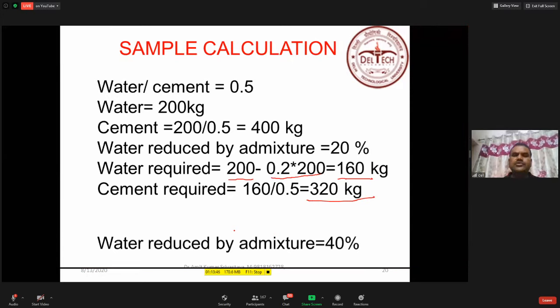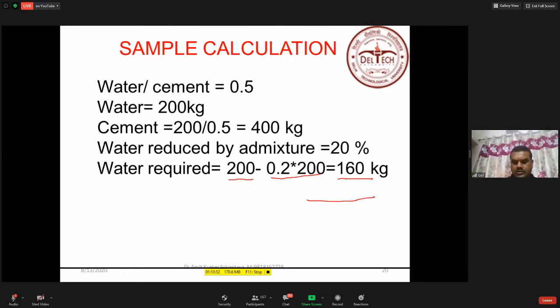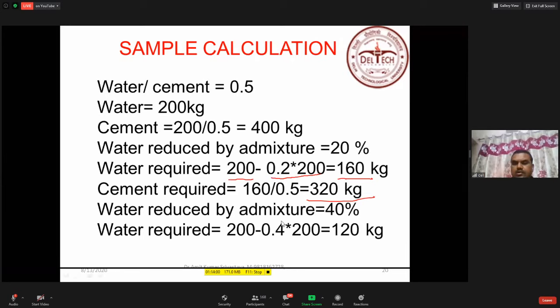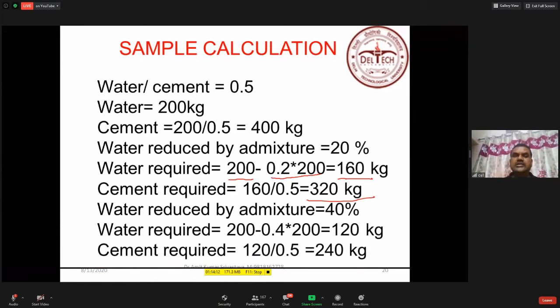Now suppose I'm using another admixture which can reduce the water by 40%. So if 40% water is reduced, then what happened? You see, water required is 200 minus 0.4 into 200. So 0.4 into 200 is 80. So now water required will be 120 kg. And you know, the water cement ratio is 0.5. So 120 divided by 0.5 will give you 240 kg cement. It means you just see, by using proper and good quality chemical admixtures, I can reduce the cement content from 400 kg to 240 kg. So this is the role of chemical admixtures.